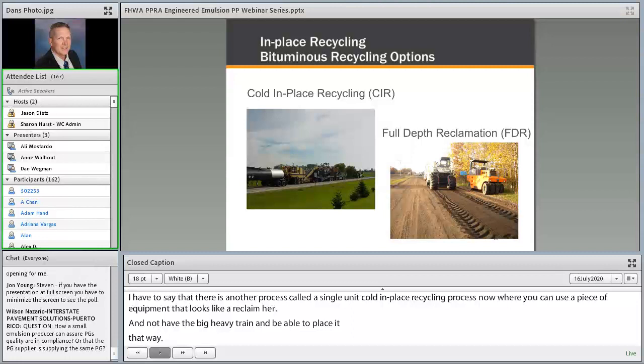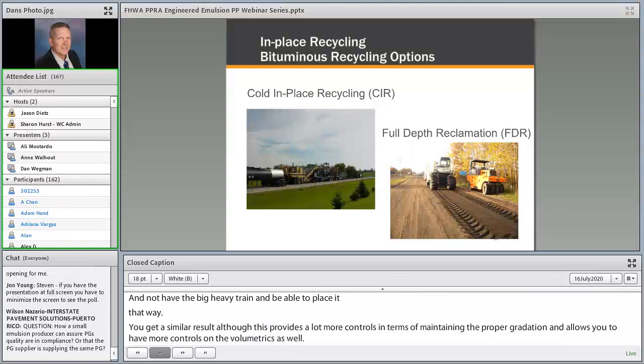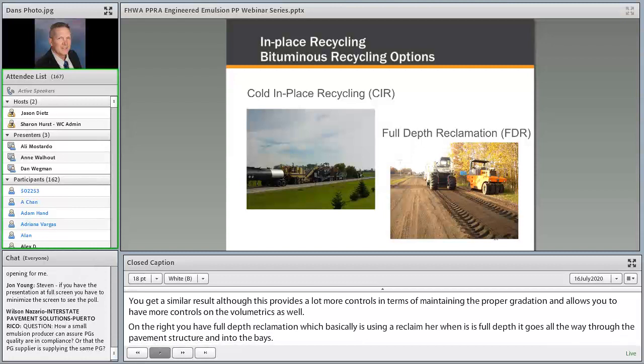And on the right, you've got full depth reclamation, which basically is using a reclaimer. When it says full depth, that means it goes all the way through the pavement structure and into the base, and you're mixing that RAP material with the uncoated base material underneath and getting a material that you're going to coat with the binder, and that is done through the reclaimer. An emulsion package is put into the reclaimer and it's actually sprayed in that mixing chamber in the laydown process.